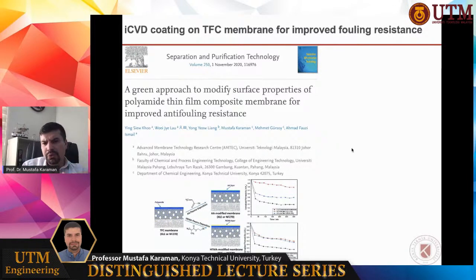A green approach. Why do we call our system a green approach? Our system, CVD, is a green technique because it uses very little energy. In PECVD, as I said before, just 1 watt. And in iCVD, the energy is just supplied to the filament, very low levels of energy. The energy consumption is very low and there is no water and no solvents. So it is a completely dry, solvent-free, green approach to modify virtually any surface. Polyamide thin film composite membrane surfaces were treated with iCVD; hydrophilic acrylic acid and hydroxyethyl methacrylate were deposited on the surfaces of the membranes, and the fouling resistance was improved dramatically after coating with such materials.